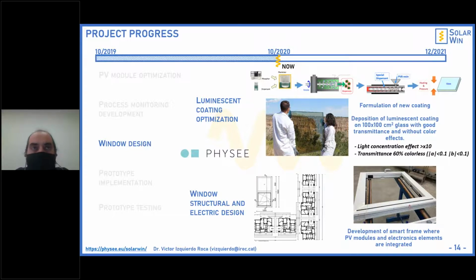The part of the window design is managed by PHYSEE, and it has two sub-tasks. The first is the luminescent coating optimization. For this, PHYSEE has been modifying the previous photoluminescence coating for a new, cheaper coating based on manganese ion, and currently it achieved transmittance around 60%, and colorless properties, and this means that we obtain a very low intrusive effect in the windows. And this technology has been developed to implement glasses of 1 square meter.